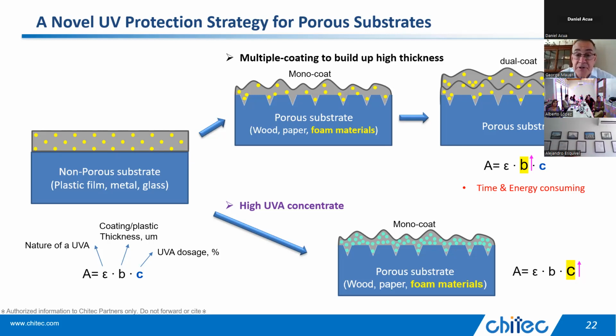So for instance, if you were to add 10% Tinuvin 1130 or Chi-Guard 5530 into a coating, you would lose coating properties. Plus the material would migrate out, but you'd lose the properties of the film because it has too much free UV absorber floating around in there. Where if it's polymerized in, you can make it highly concentrated. And we went as high as 20%, but 10% is probably as high as people would normally go. You can make a really concentrated UV absorbing film that's thin and protects the substrate that is sensitive to light. So this is a great way to get a very concentrated UV absorbing film.